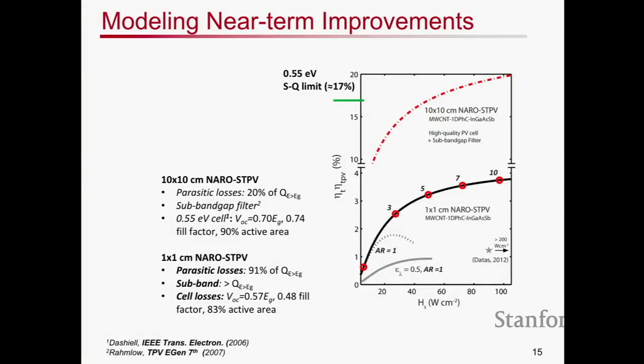What I forgot to mention is that we're using pretty specific cells in this case. We're not using silicon cells, which are commonly used for the PV market right now, because with silicon the band gap is higher, so you would probably have to operate around 2,000 degrees Celsius. So we're looking at these low band gap cells, kind of the limit of what we can get to in terms of temperature, such that we can deal with the contacts and measurements that are non-trivial as you get to higher and higher temperatures. So this is really the first step.